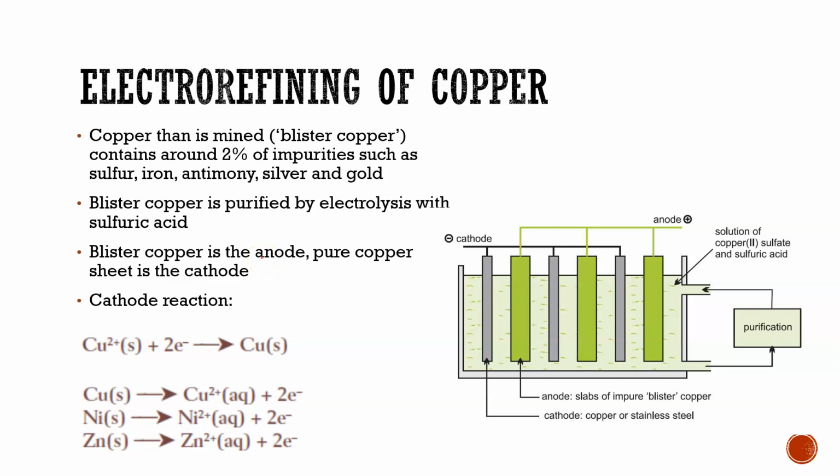As the reaction proceeds, copper at the anode is oxidized to produce copper ions. Copper ions from the solution at the cathode will be plated onto the cathode, which means that because this was a copper bar, when we pull this cathode out of the cell, we are going to have 99.9 or 99% pure copper plated onto that copper bar.